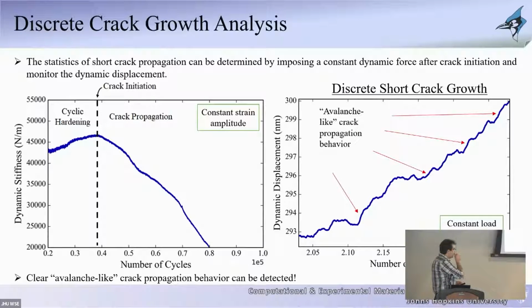But then we thought, okay, how do we actually extrapolate information related to how these cracks actually propagate? So we stopped the experiment. This was done through a constant strain amplitude, and we decided to drive this experiment with a constant load amplitude, because when you do the load amplitude control, you can actually measure the amount of displacement and the changes in the displacement associated with the crack opening or with the crack closing. So if this dynamic displacement is flat, that basically means that at the same constant loads, the crack is not propagating at all. But if it increases, that basically means that the crack is actually opening, because now it's much more compliant, so you can get more opening. And if it's decreasing, that means that the crack is closing.